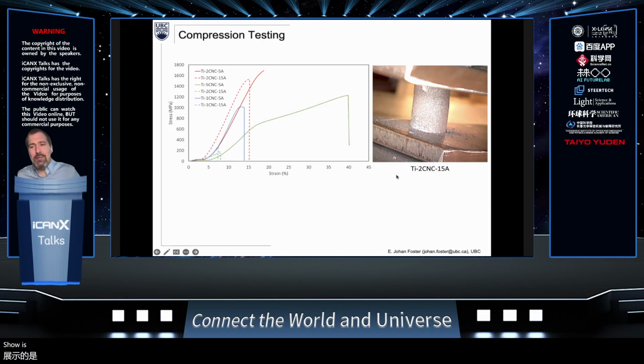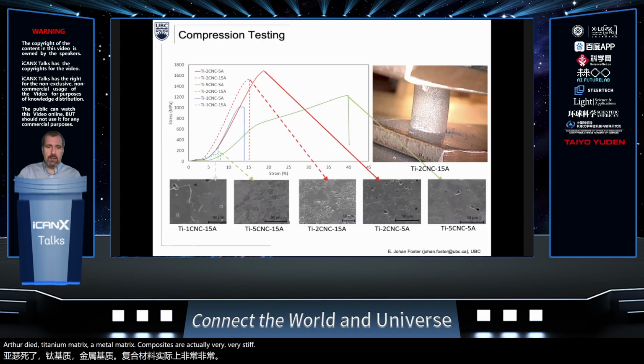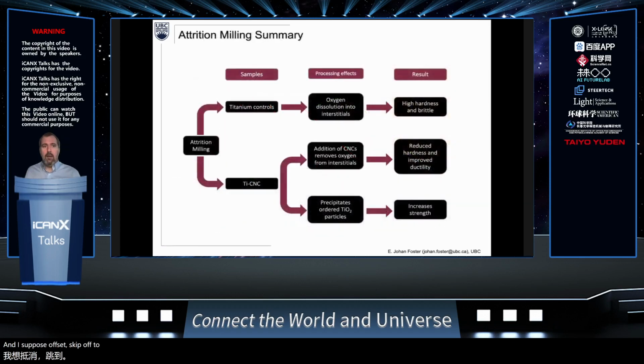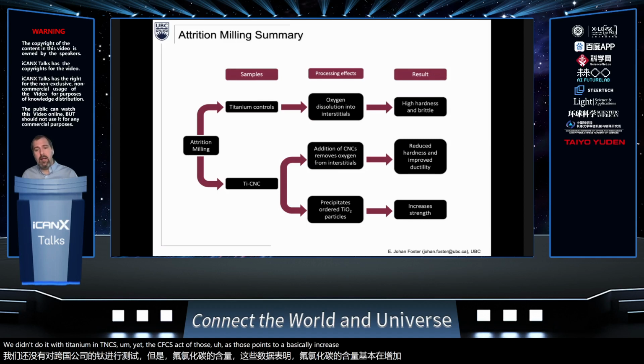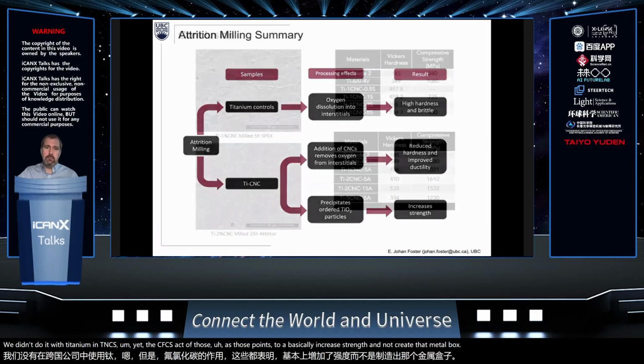All I show is the compressive strength of these titanium matrix metal matrix composites, which are very, very stiff. And I'll skip up to what this actually does. When you do attrition milling on titanium itself or with a few other additives, the oxygen dissolves into the interstitial sites of the titanium, and you get very hard, very brittle materials. When you do it with titanium and CNCs, the CNCs act as those points to increase strength and create that metal matrix composite.